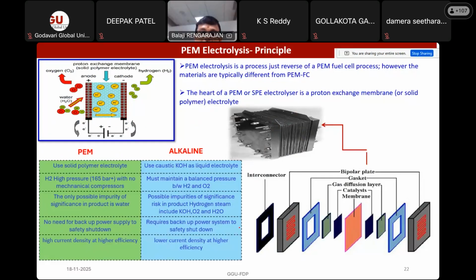You cannot operate the cell at high current density, and because of that, you cannot produce more hydrogen in a particular area. So if you want more hydrogen, you have to increase the area. Whereas in the case of PEM, that is, proton exchange membrane based electrolysis, the key advantage is that you can pump more current in a particular area. Up to 1 ampere or 1.5 ampere per centimeter square current you can pump at the same voltage of 1.5 or 1.8 volt. The beauty of this technology is that the membrane will do the job of conductivity.